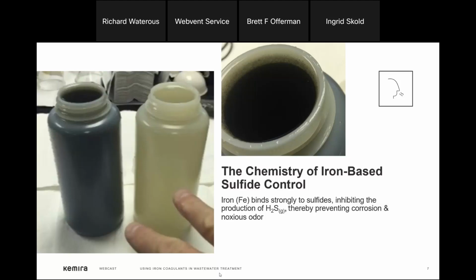Both bottles in the photo are samples of raw municipal wastewater plant influent containing high levels of dissolved sulfides drawn from a customer's headworks. The bottle that is black has had iron sulfates chemistry added to bind the sulfides present. The black micropin flock that you observe is iron sulfide, the result of the iron chemistry pulling the sulfides out of solution and complexing with it, with the resulting insolubles precipitating out in the plant's treatment process.